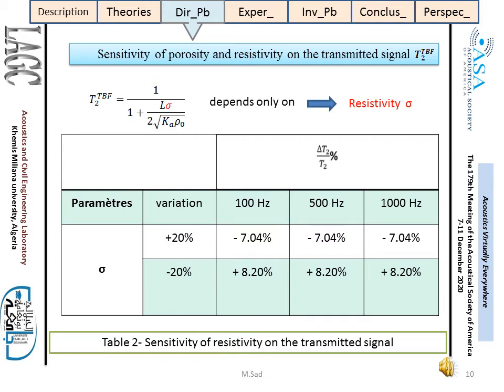At very low frequencies, the sensitivity of the porosity on the transmitted signals given by T1 is negligible, and this sensitivity increases with frequency. It's therefore preferable to use the expression T2 to characterize the porous medium in the very low frequency range, because this expression has the advantage of being independent of frequency and porosity and depends only on the flow resistivity.